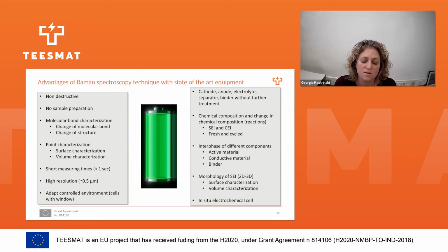By this means, we can study the SEI, the solid electrolyte interface, and the cathode electrolyte interface. We can study the fresh and the cycled materials. We can understand the interface of the different components by performing 2D mapping, so we can see how the active material is related to the conductive material, to the active carbon, and also what effect the binder has. And in terms of morphology of the solid electrolyte interface, we can have surface characterization, and under certain circumstances also volume characterization of it.